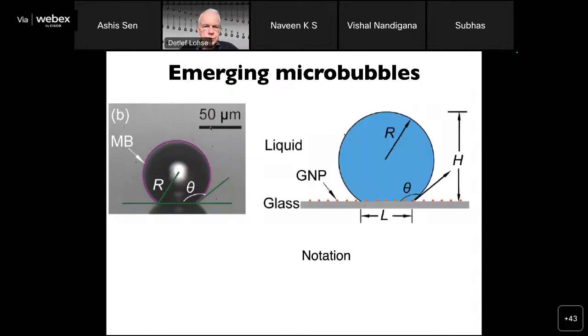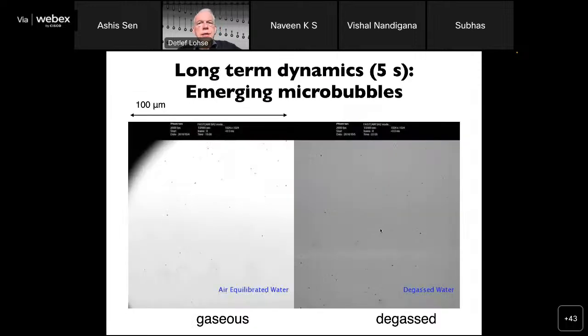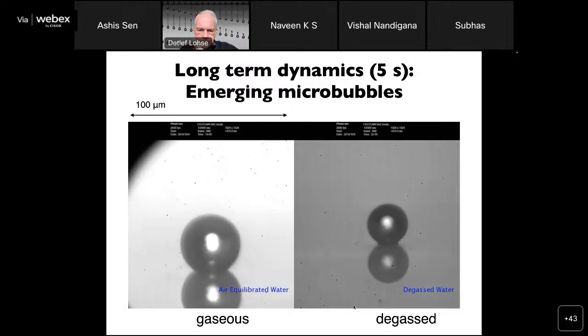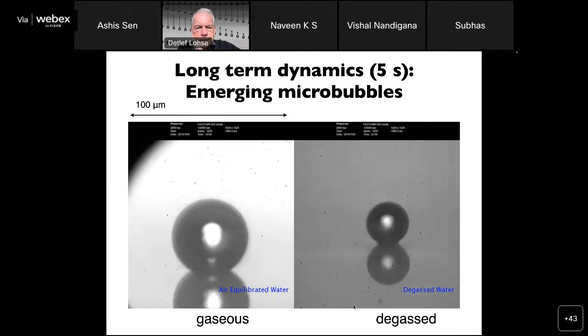So here you see the emerging bubbles, and we have radius, we have the angle, and there are, in fact, several nanoparticles under this emerging vapor bubble. And here you see our observations on a long time scale. This is now a time scale of 5 seconds, and you see emerging bubbles on the left for water which contains gas, and on the right for water where we partially degassed. You see that for the gaseous water, the growth of this bubble goes on much, much longer, whereas here it ceases at some point. So quite different behavior. Already here we see that gas plays a major role.